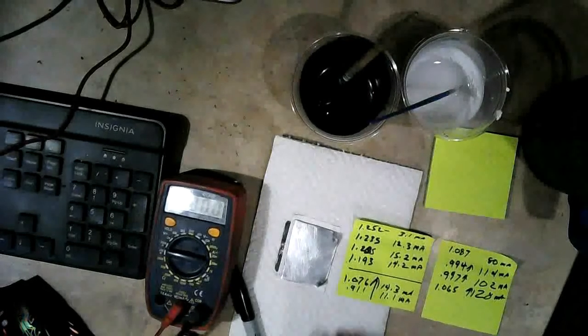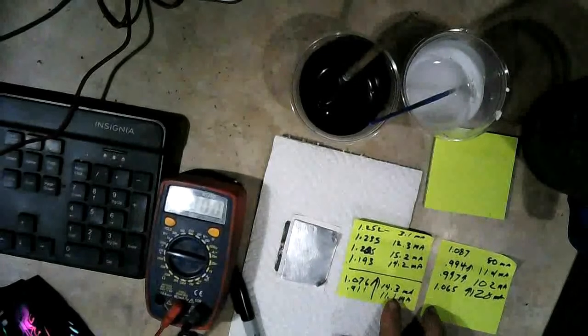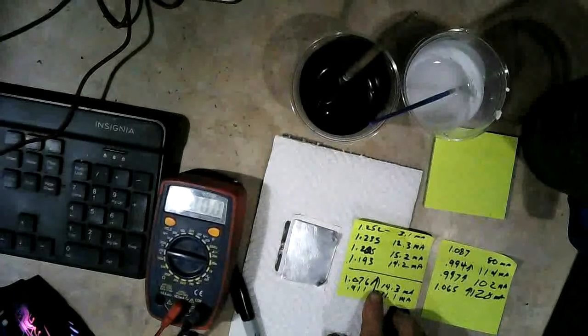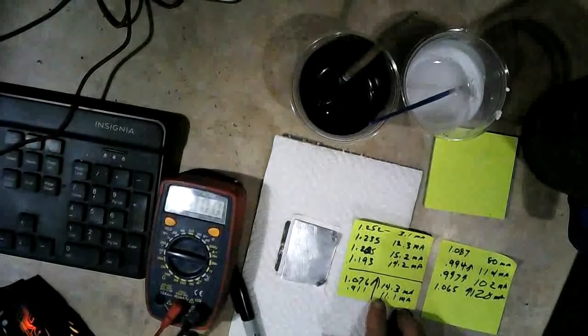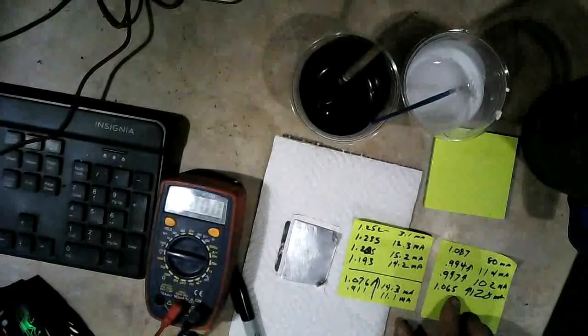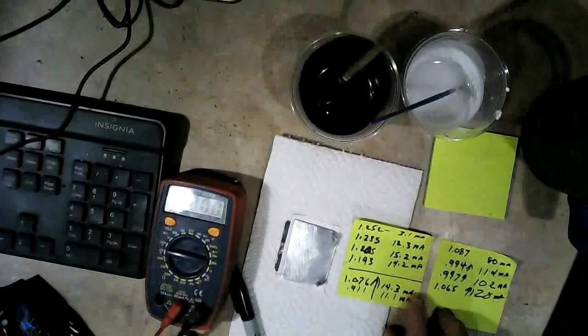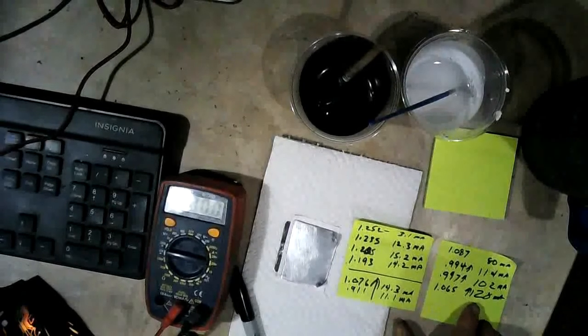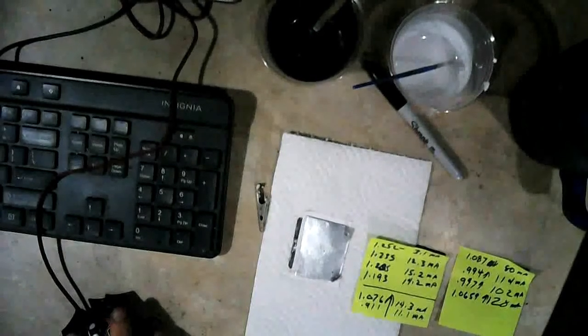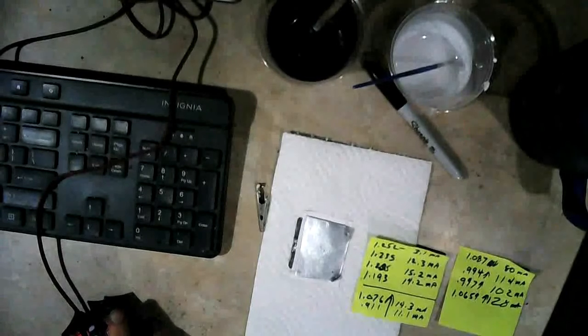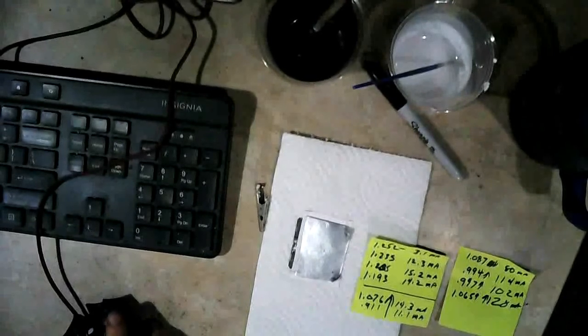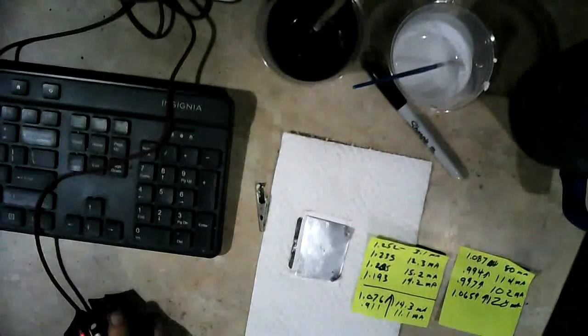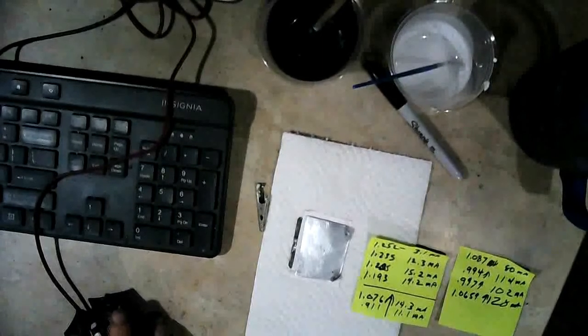Alright, I'm back again. Now, comparing our results from these experiments here, you can see that the carbon felt experiment led to a memory of an old crystal battery experiment that led to the improvement here in the thin film borax separator by encapsulating the whole thing. And we ended up, we had the best we had was 50 milliamps and we nearly tripled that. The real exciting part about this experiment here is that we got it up to 128 milliamps with no electrolyte, just water. So, you know, why use electrolytes that dirty your cell up? Why not keep it real clean? And I'd rather just have a cell run on water than I would have it run on electrolyte, if I can.